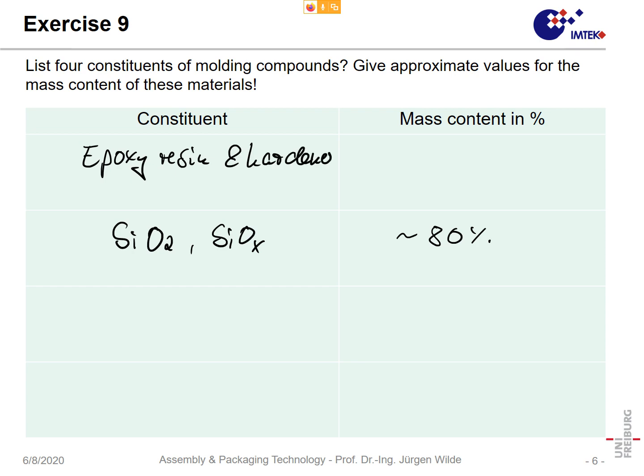So for instance, if we would say 15% roughly plus maybe 2%. So the content of epoxy, which keeps it all together, sticks it together, is much lower than the silicon oxide. The silicon oxide brings down the CTE of that material. What else do we have? We have carbon black. It's somewhere in the percent region. So it's important not to have light come into the package because many semiconductors are light sensitive.